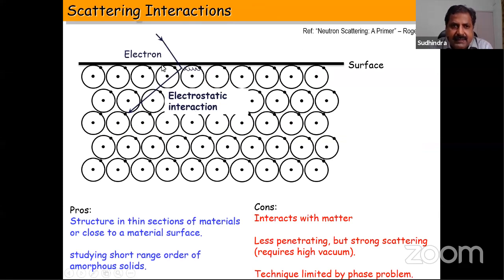In electron diffraction, the electrons interact with the outermost electrons in the sample by electrostatic interaction. The advantage of electron diffraction is that you can look into the structures of thin sections of materials which are close to the material surface. It helps in studying the short-range order in amorphous solids, for example. But there are certain disadvantages also, like the electron beam starts interacting strongly with the matter. It cannot penetrate too deep into the system. To do electron diffraction, you need very high vacuum, so the experimental conditions are very stringent. And electron diffraction is also limited by the phase problem.